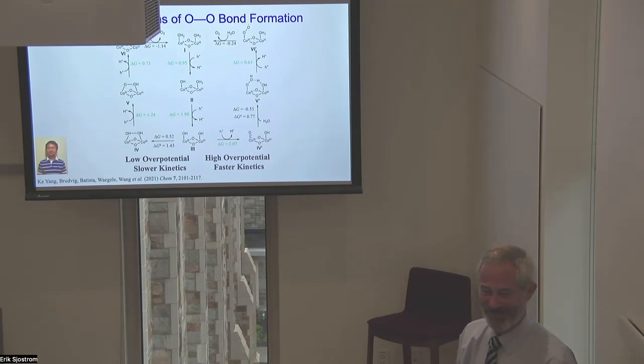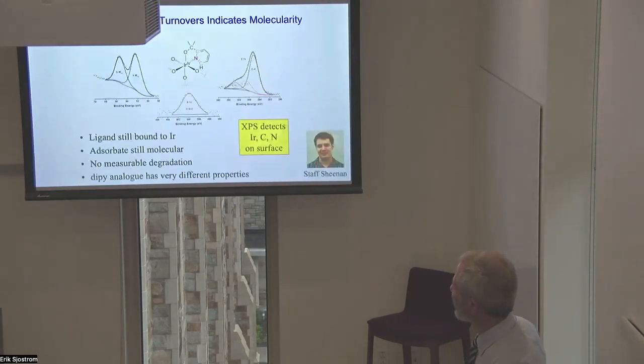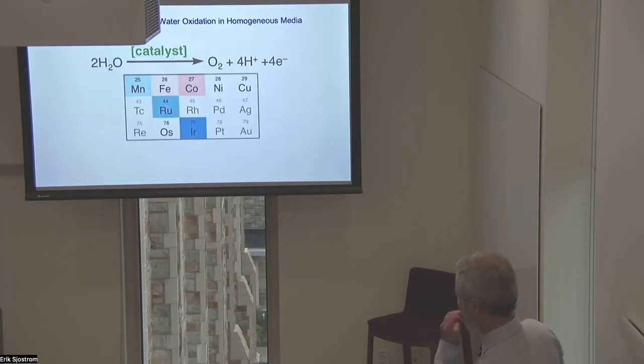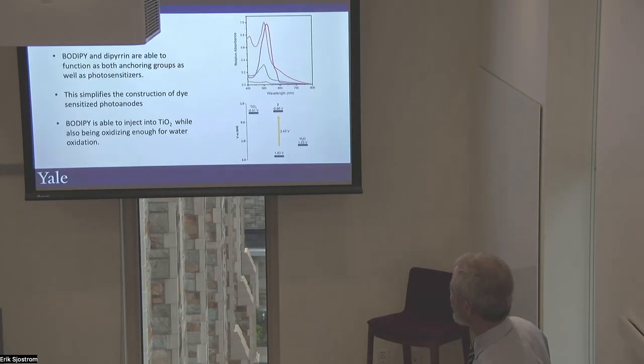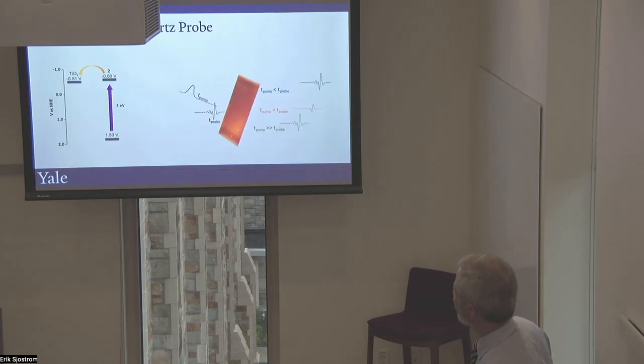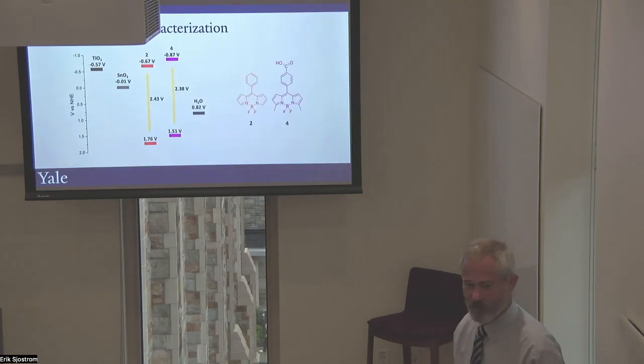Thank you. And I have another question about the first part, the photoanodes. I'm not really familiar with that part, but I remember that if we just change the functional group of the dye, we can shift the HOMO and the LUMO level there. I saw that the conduction band of the TiO2 and the dye's level are very close. So is it possible to modulate the functional group to make that gap a little bit bigger? If it is bigger, is it possible to accelerate the charge transfer or suppress the back electron transfer?